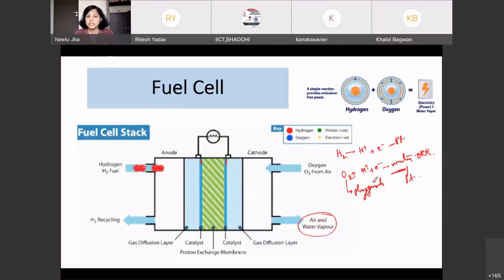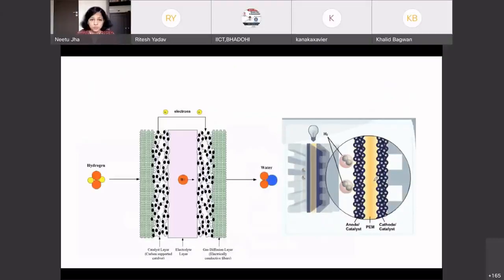So it's not so easy to just increase the content of platinum. We will have to do something. So what has been done is that platinum nanoparticles are coated on supports which are mostly highly stable. Amorphous carbon is actually being used, but it is not very stable. So carbon nanomaterials, carbon nanotubes, graphene are being studied. So you have these catalyst supports, and we are making platinum nanoparticles of very small size, 2 to 3 nanometers, and depositing them on a substrate which is stable, and then make the catalyst layer, right?